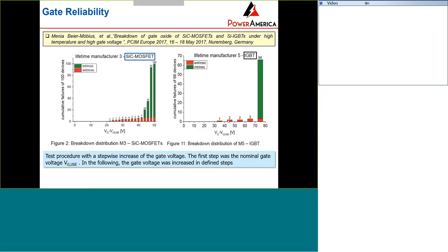The x-axis shows the voltage beyond the operational voltage on the gate, so the x-axis is VG minus VG use. VG use is normally the gate voltage the device operates at when you fully turn on the device. The y-axis is the failure number out of 100 devices, which is the sample size they used. The test procedure is to increase the gate voltage from the nominal VG use, gradually increasing to gate rupture or gate leakage current from the stress.